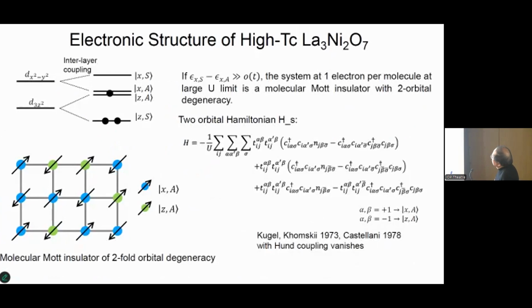So if I consider the next simplest case, this orbital is well above, so I have 1 electron for these 2 orbitals. Okay, so that's the case. That two-orbital Hamiltonian can be written in the large U limit in such a form. It's a little bit complicated, but it was well studied many years ago by Kugel and Khomskii and by Castellani. And if I set the Hund's coupling to vanish, it reduces to this form. So essentially, this is a Mott insulator, but with 2 orbitals: a spin-1/2 and an orbital spin-1/2 degree of freedom.